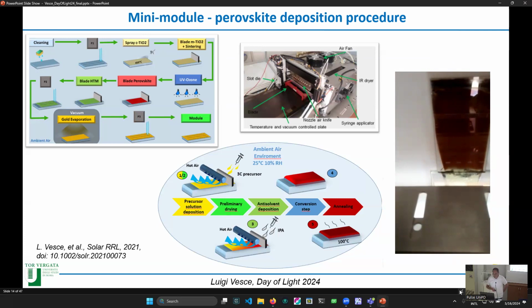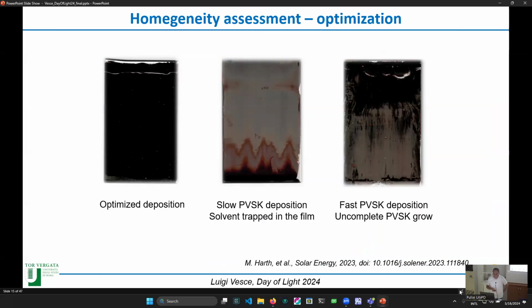Then you have a step of annealing. Here are some pictures of the homogeneity assessment. These pictures are from a work that we did in collaboration with TUM, working on machine learning of this process. We got a lot of characterization, but here it's easier to understand three pictures. On your left, you can see the picture of an optimized deposition. Then in the middle, to show you how a single process parameter can play a role in the deposition of a good perovskite, and also of the other layers.